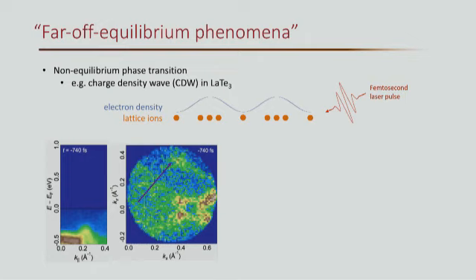You can't see much intensity here because, as Yafan said, when you go into the charge density wave state, much of the Fermi surface is gapped out. That's why you didn't see much intensity. Here I'm taking a specific cut to see the energy versus momentum dispersion relationship. And this is basically the band that's supposed to cross EF, but it actually doesn't cross the Fermi energy. And for this particular material, the energy gap is pretty huge.